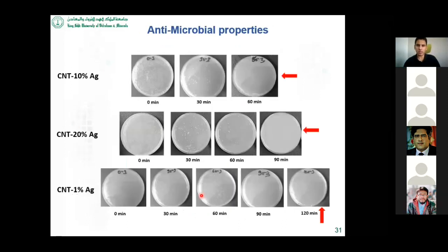This is the schematic of some of the study we did. As I mentioned, the carbon nanotube modified with silver, these membranes were able to kill all the bacteria in 1 hour. Similarly, a membrane with 20% silver loading took almost 90 minutes, and 1% silver loading took around 120 minutes. So here you can see that 99% is CNT, okay, and 1% is the silver.